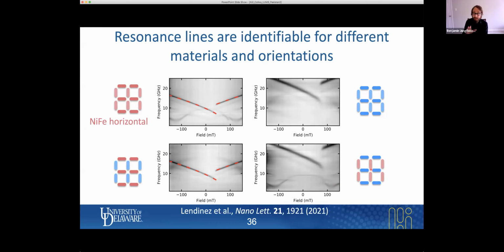And again, these are real calculations. So we see here the nickel iron elements, which are in the horizontal direction, shown by these red dashed lines. The nickel iron vertical elements are shown by these dotted lines. Then I'm showing the cobalt iron horizontal elements by these dashed lines, and the cobalt iron vertical elements by these blue dotted lines. So we get a pretty good idea about what is going on in this system, but there are other modes which we are not able to calculate analytically, and for that we use micromagnetics.